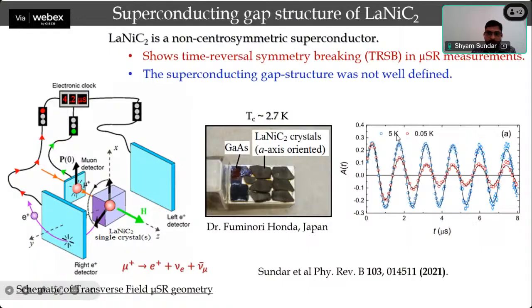in a whole temperature range starting from 5 Kelvin down to 50 millikelvin. As you can see, 5 Kelvin is in the normal state, which is a paramagnet. You do not see any relaxation here. But when you measure at 50 millikelvin, you see a huge relaxation, which is basically because of the vortex state, as I showed you in the previous slide, which forms a vortex lattice of hexagonal type, which has a magnetic field distribution. Because of this magnetic field distribution, you see this muon depolarization.